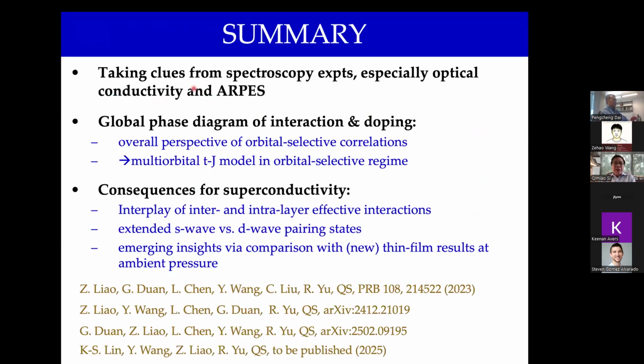We took clues from spectroscopy experiments, some that exist at a very early stage, some that have come up since that time, and I emphasize for the normal state the implications of optical conductivity and angle-resolved photoemission spectroscopy, and how that has, at least for us, anchored our theoretical considerations, especially concerning the correlation effect and orbital selectivity of the correlation effect.